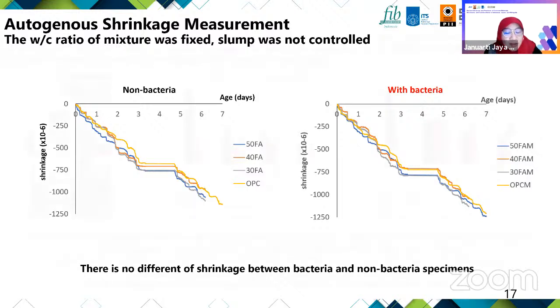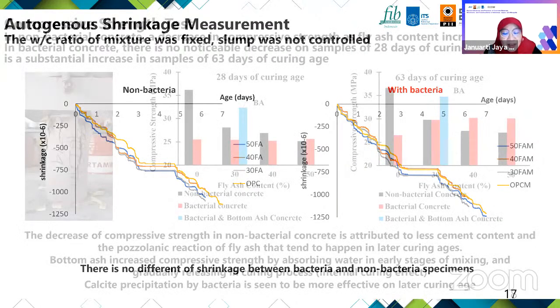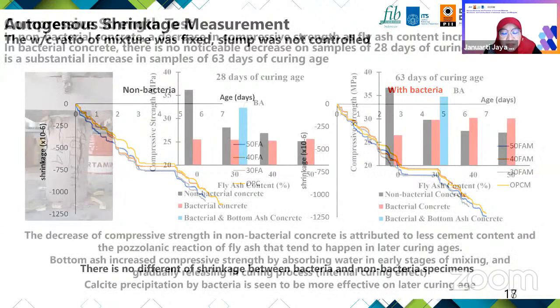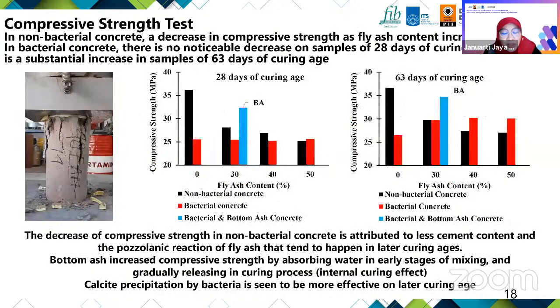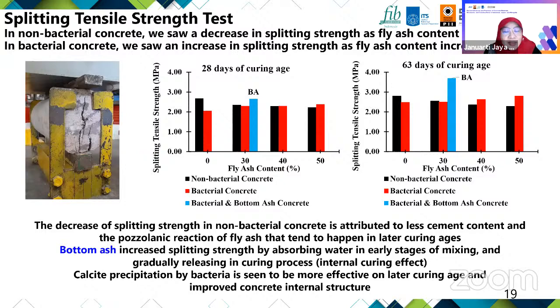For the compressive strength at 28 days, as expected, concrete with higher fly ash content has lower compressive strength. However, at the later age, at 63 days, we found that the rate of strength increase is higher than the normal specimen. It is very pleasing to see that the effect of the internal curing by bottom ash worked very well, as did the effect of the bacteria filling the concrete pores during hydration. And as expected, because of the denser concrete pores, a higher split tensile strength is shown by specimens containing bacteria and bottom ash, as can be seen in this result.